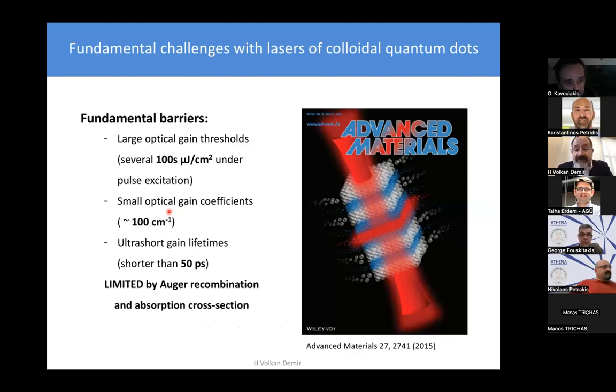And these fundamental barriers actually came from the material, interesting properties of the gain material we used. These are conventional colloidal quantum dots at the time, the best materials we could find and indeed generate. However, the gain thresholds we were able to observe with them always were several hundreds of microjoule per centimeter square under pulse excitation, and not in the thousands range. The root cause is the gain coefficient is small. It's just 100 inverse centimeter. And this is accompanied by, as expected, ultra short gain lifetimes, typically shorter than 50 picosecond.